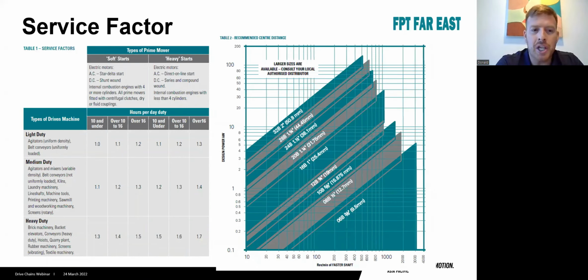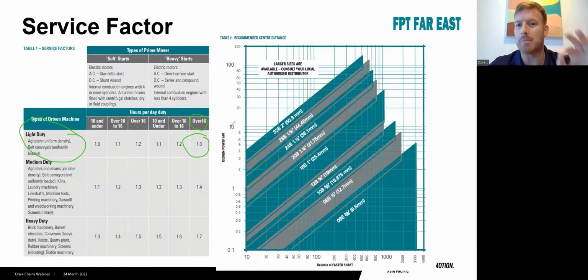If it's a light duty, and that light duty is operating with heavy start, so direct online, like the video we saw, and operating for more than 16 hours, we recommend a 1.3 service factor. So what that means is we take the installed power in kilowatts, and we multiply it by 1.3. For example, if I have a 10 kilowatt motor, and I multiply by 1.3, I get 13. Is that correct? Somebody check me. So I get 13 kilowatts as my design power.